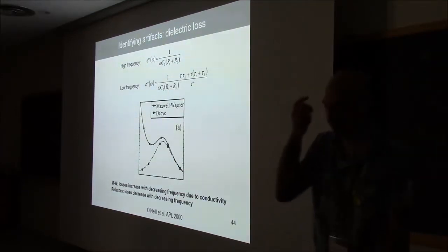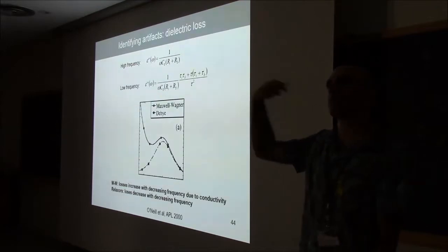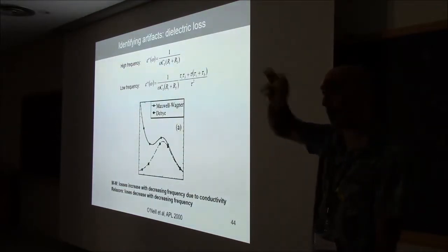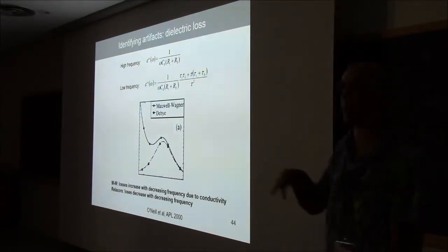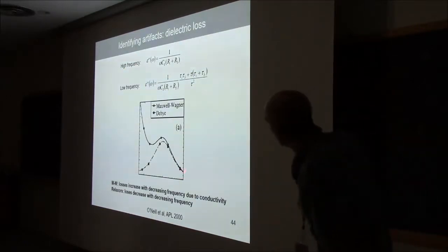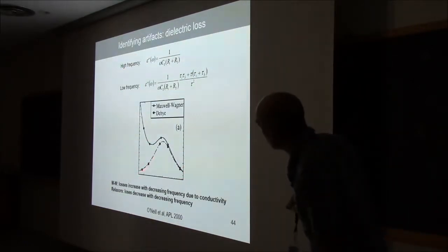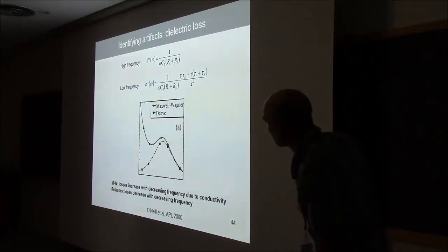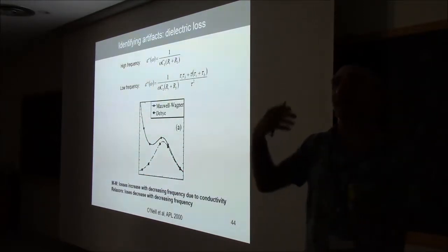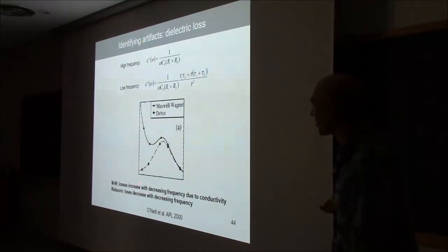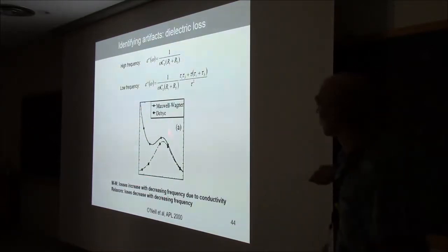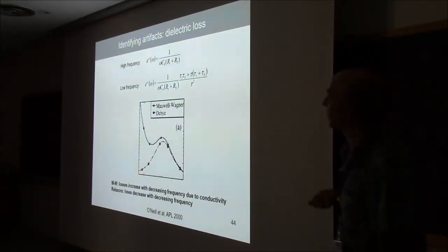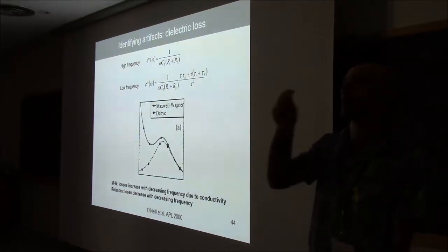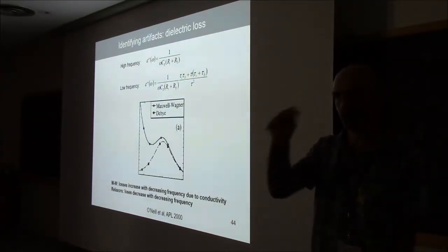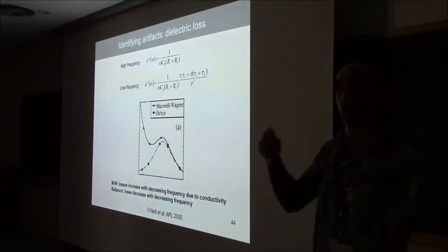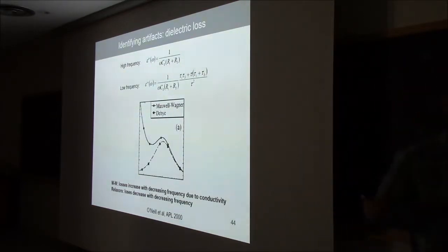And you can look at the loss, and this is what I was saying earlier about the relaxers. So in relaxers, as you increase the frequency, the dielectric loss goes up. So as you decrease the frequency, the dielectric loss goes down. This will be the shape of the relaxation peak in a relaxer or in any dielectric material. In a material that is leaky, that is not a relaxer, at low frequencies, your material is becoming more lossy, so your losses go up. Okay? So the frequency dependence of the dielectric loss is the absolute bulletproof proof. Yeah? Okay.